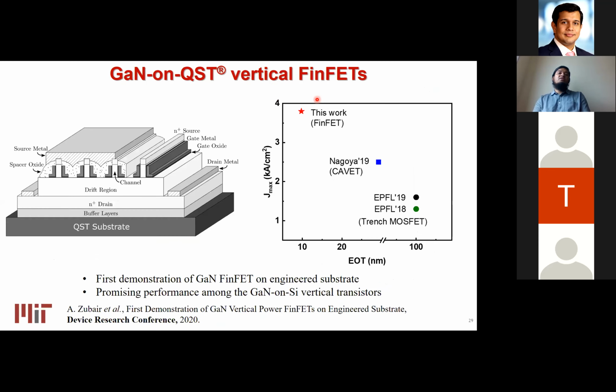And recently we started working with this company in collaboration. They are giving us the substrate, and we tried to fabricate this vertical power FinFET on this substrate. And we're starting to get very good results from our first try. So we recently fabricated our first devices, and on the right-hand side, we have this plot with the EOT of the gate dielectric, and on the y-axis the maximum current capability. And these are the other devices in the literature where people fabricated vertical GaN transistors on silicon-like substrates. We found that our devices are performing pretty well, and that really shows a promising performance among the GaN-on-silicon vertical transistors for commercialization in the future.